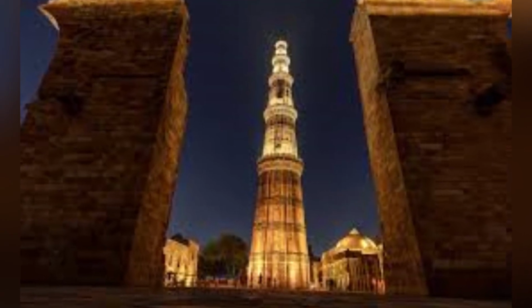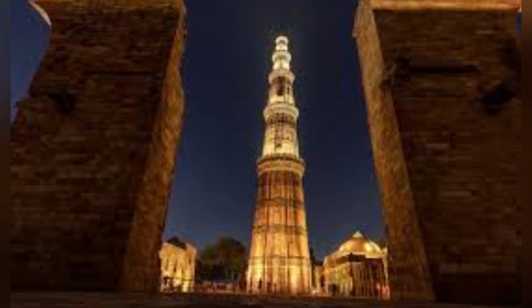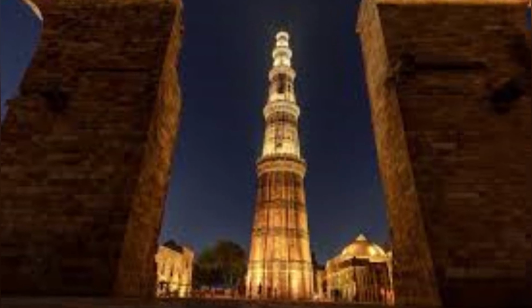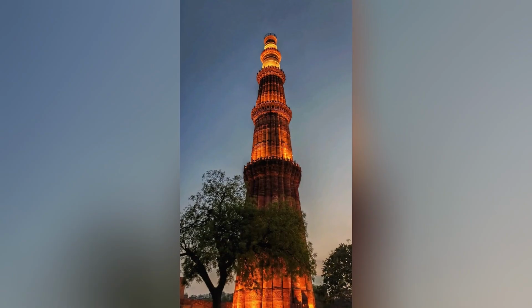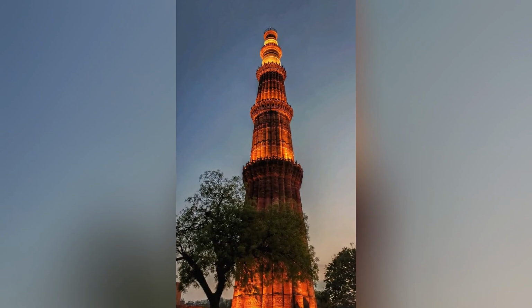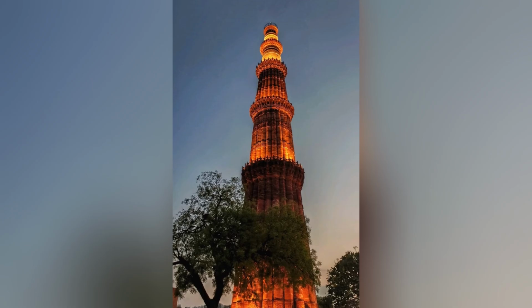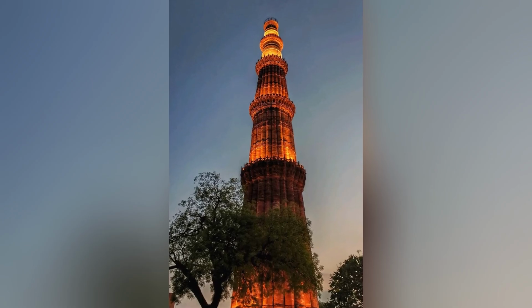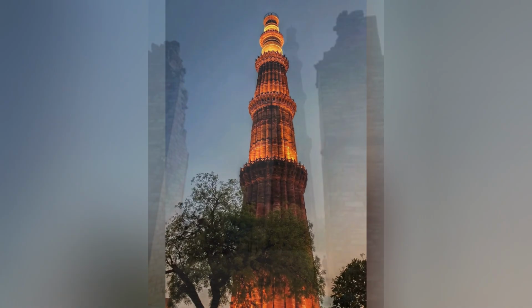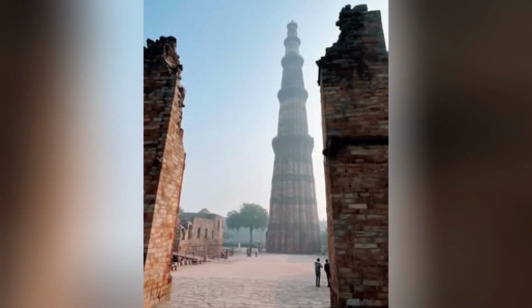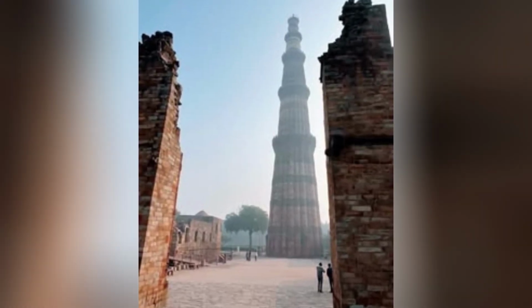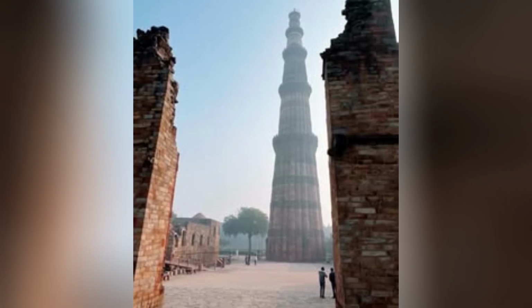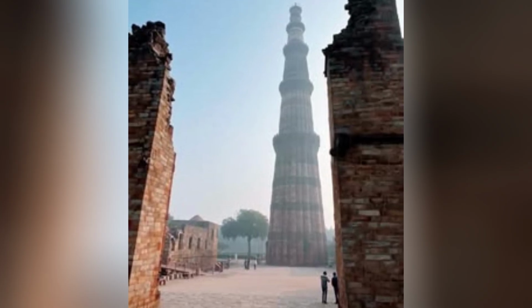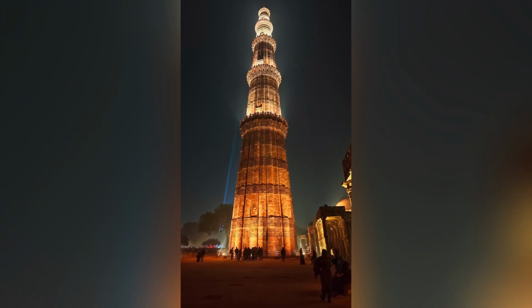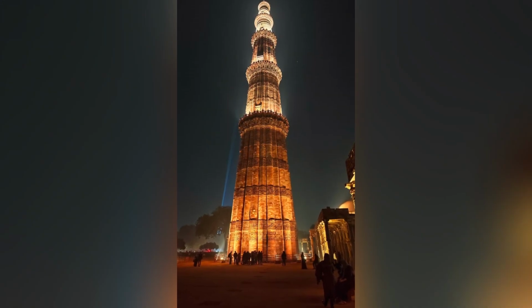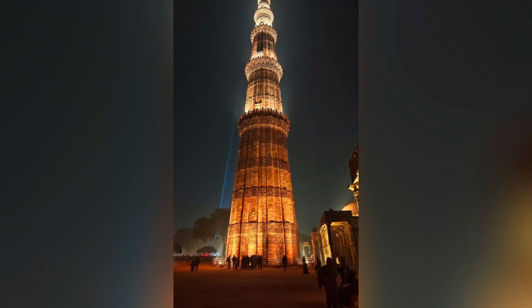The time required for the film to develop its maximum protective capability has been estimated by Balasubramaniam at approximately 300 to 400 years, a period during which the film transitions from a porous, partially protective state to a dense, fully protective state. The dependence of the film formation process on the specific climatic conditions of Delhi raises the question of whether the pillar would have been equally well preserved if it had been located in a different climate.